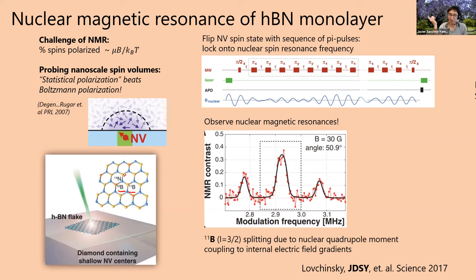But the problem with NMR in general is that you need to polarize these spins to actually get some net magnetic field, or else all the spins will just cancel out. You don't get any net polarization. So this usually means that you have to apply a big magnetic field, maybe even go to low temperatures. And this is in the end why when you get an MRI scan, they put a big honking magnet on your head.